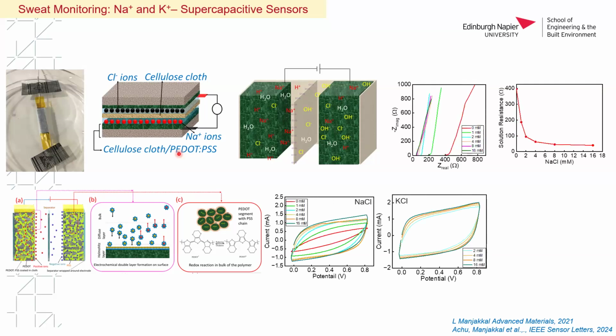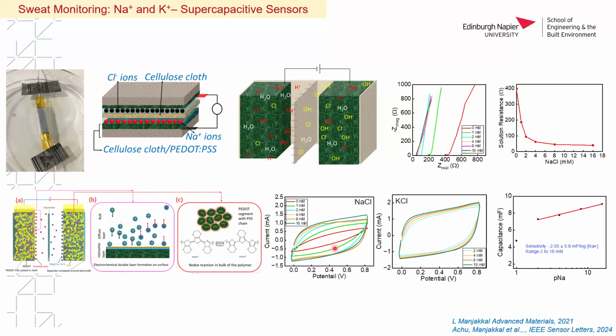We did another sensor where we changed the sodium concentration. For example, depending on the human's health condition, the sodium chloride, the salt, may change. So the conductivity of the electrolyte will vary. We changed the electrolyte conductivity, and we found that this variation influences the energy storing or the capacitance generation of this device.